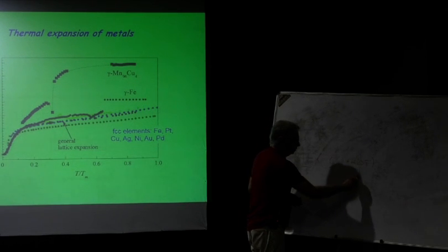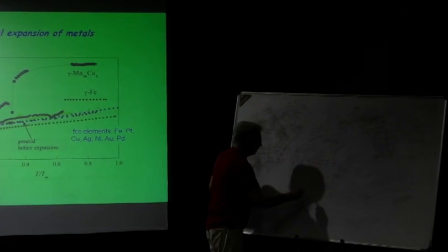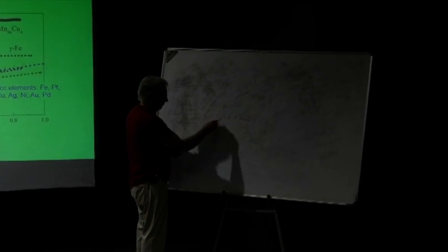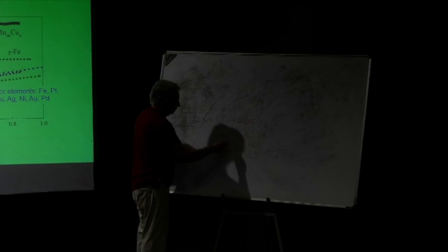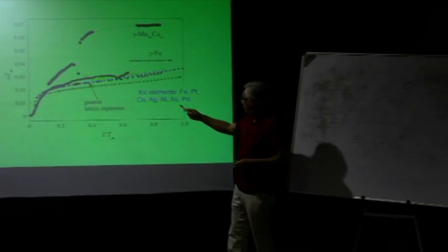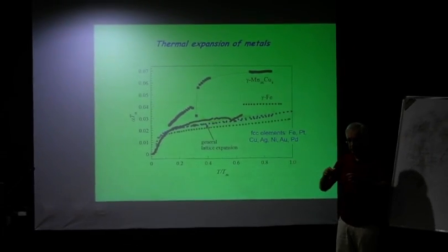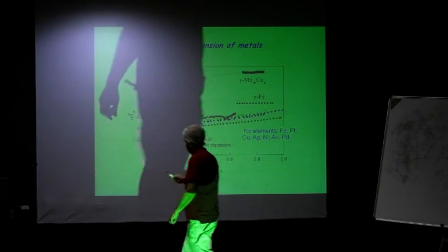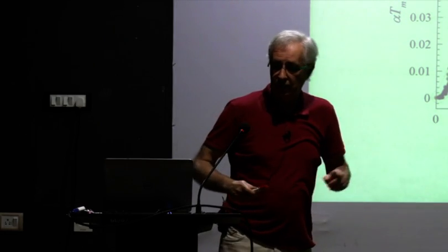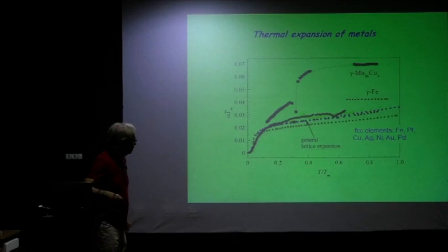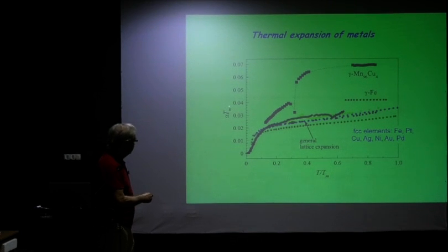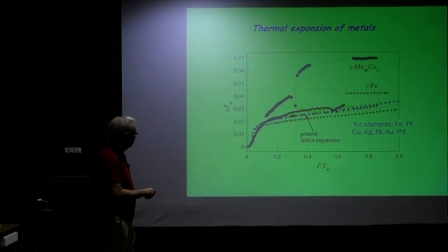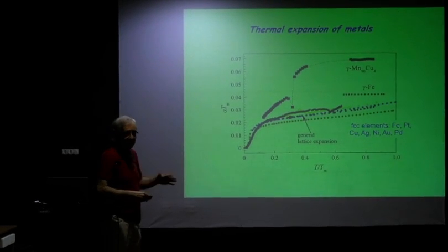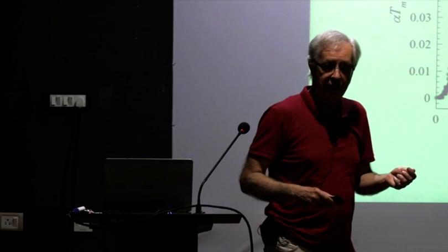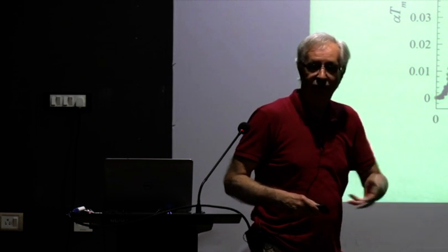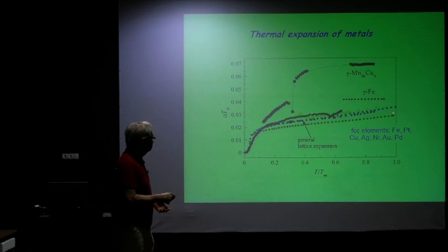So this here would be alpha Tm. So that on this side we would have L minus L0 divided by L0. So this would be delta L over L, and this would be alpha Tm. Now, this is why we plot alpha Tm on that side and try to understand the length change. So alpha Tm is basically the length change at the melting point. You see here that when you plot this alpha Tm for all these elements, you find that they all lie on this so-called general lattice expansion curve. So all cubic materials essentially expand by the same amount before they melt. They expand by about 3% before they melt.